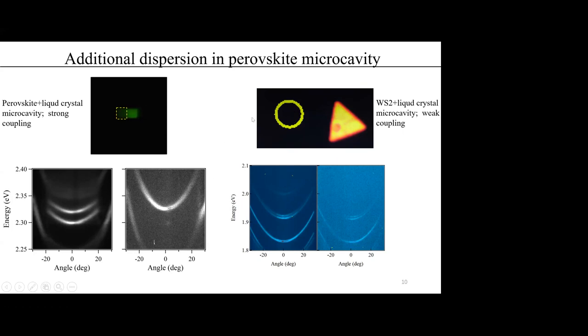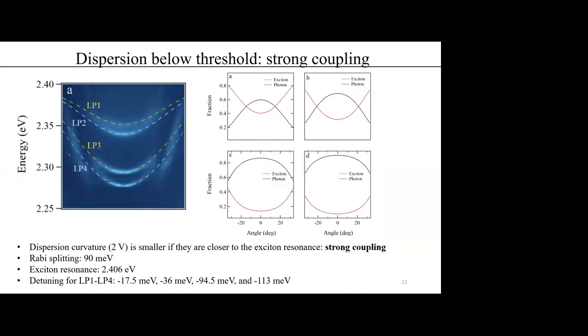So these results clearly show that a strong coupling between the perovskite excitons and the cavity photon modes is observed in our microcavity. And the existence of this large curvature dispersion can be used to prove the existence of strong coupling within the microcavity. So in the following, we just focus on the lower branch polaritons of the microcavity.